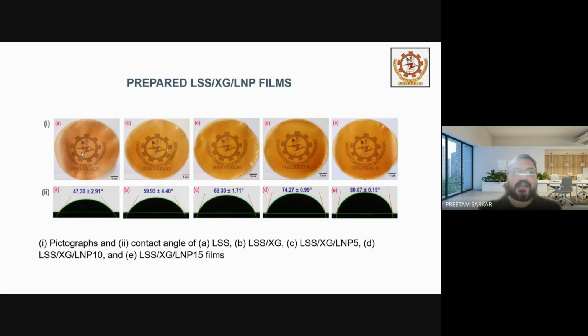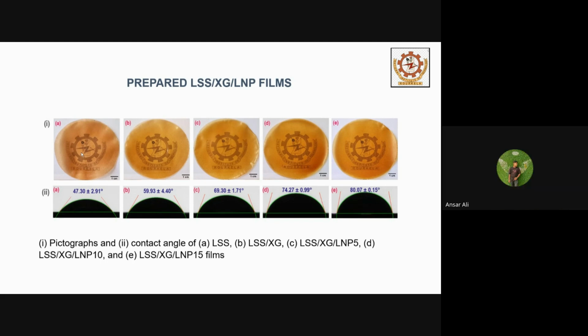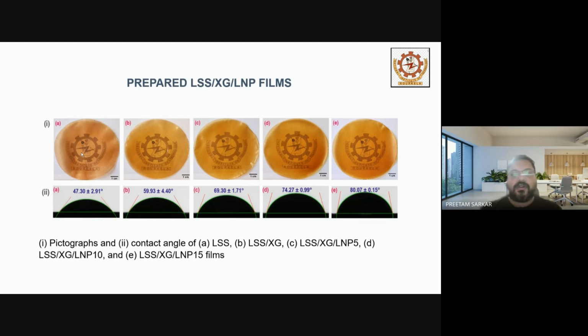We want to have the surface as hydrophobic as possible. For the hydrophobicity, we have a standard technique called contact angle measurement. We use a goniometer, or a surface analyzer, also a goniometer, to measure the surface hydrophobicity. As you see, the higher the value of the contact angle, the more hydrophobic the surface is. We want to have more hydrophobic surfaces.